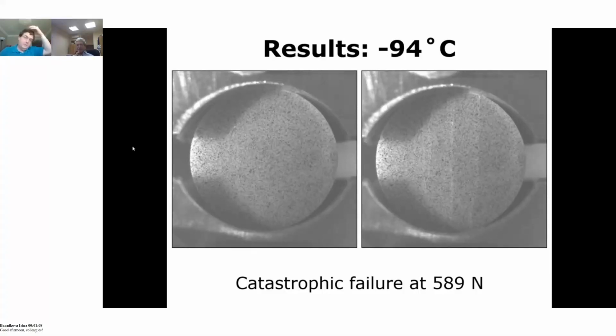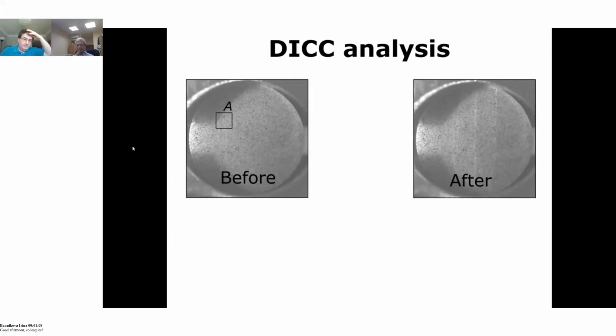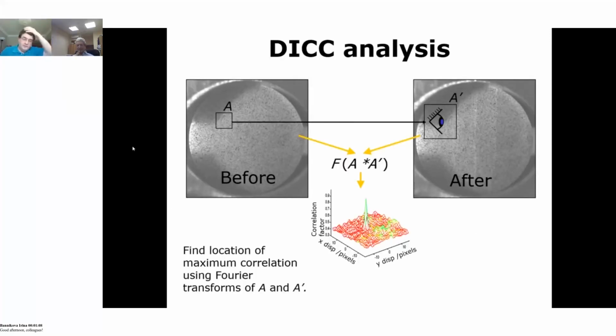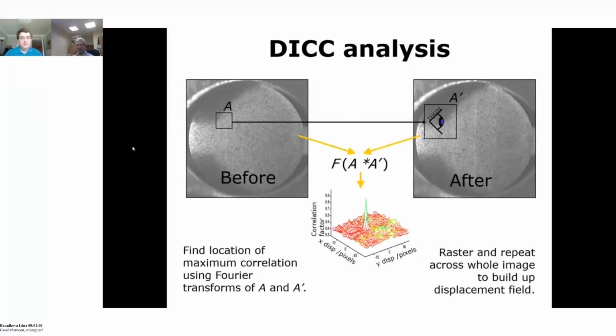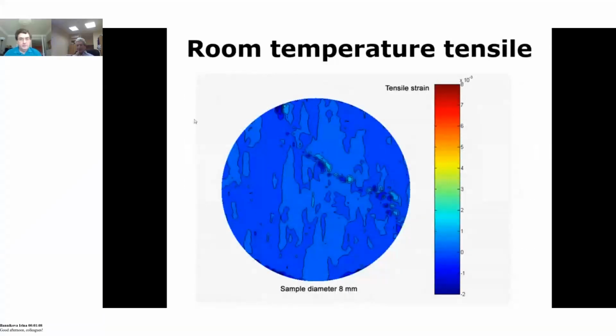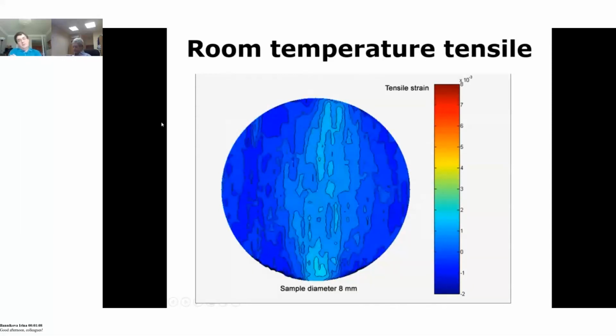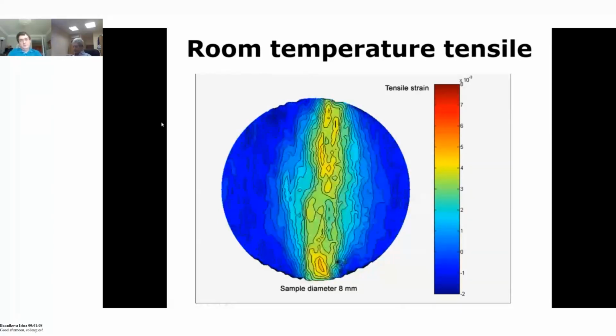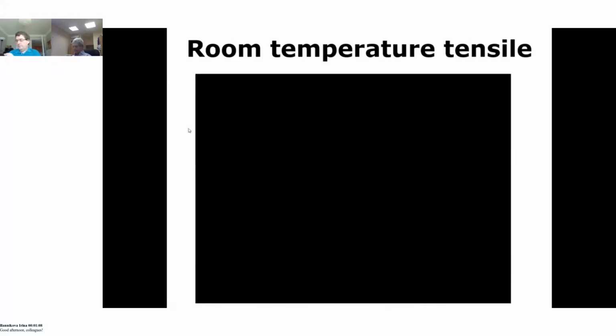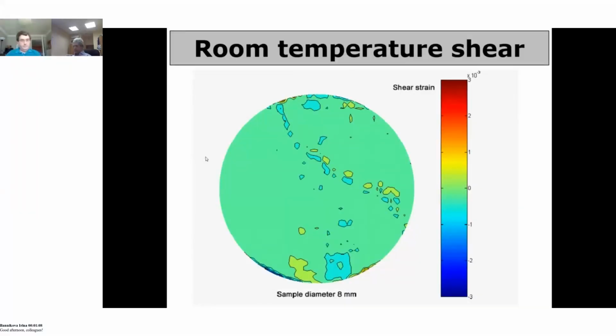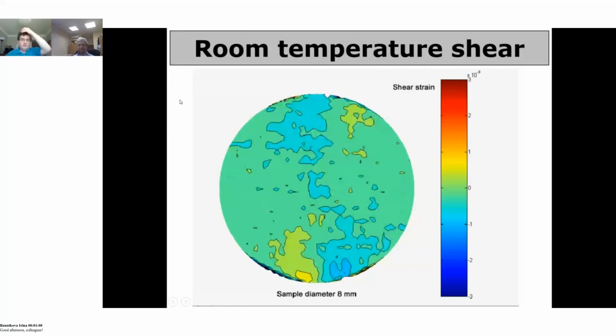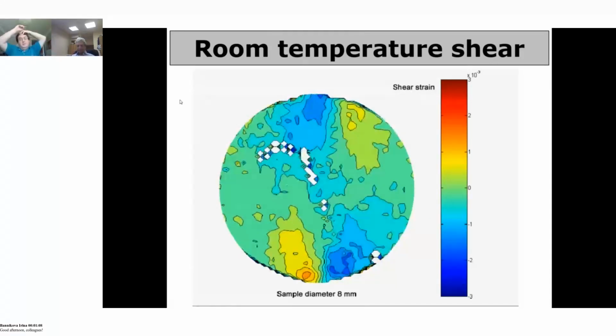So we did the image correlation analysis, finding that correlation peak. Again, you've seen this particular image a fair few times now. And we can build up the displacement field. So this is the response we got in terms of tensile behavior in the material. So you can see a kind of general shape in the system. So I'll play that again. This is the shear in the system, and we can see the lobes there. So play that again.